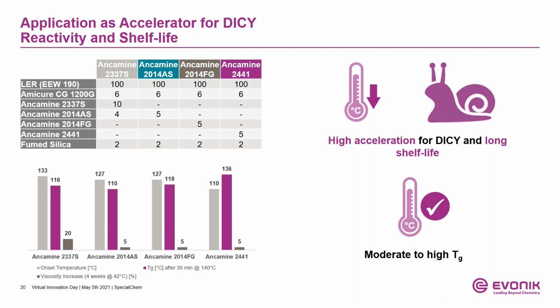Ancamine 2441 shows the best performance set with a remarkable shelf life at also elevated temperatures. Against this, Ancamine 2337 and the Ancamine 2014 grades are on a very similar level here, whereby it must be noted that the curing reaction of Ancamine 2337 shows a two-step mechanism. The onset temperature shown here is the one of the second curing step detected. So in practice, it can be actually lower than shown here.